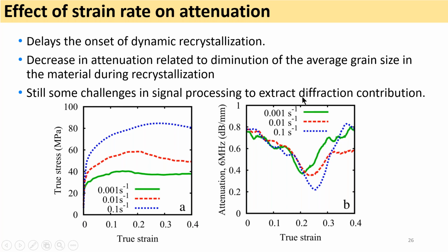So this gives us a promising result, but at this stage, I would just encourage everyone to continue this type of study and try to work towards correctly eliminating this problem of diffraction. As the sample shape changes during the deformation, it becomes a little harder to interpret, to separate the diffraction contribution from the scattering contribution in the waveform.